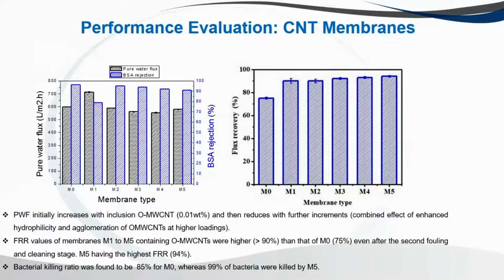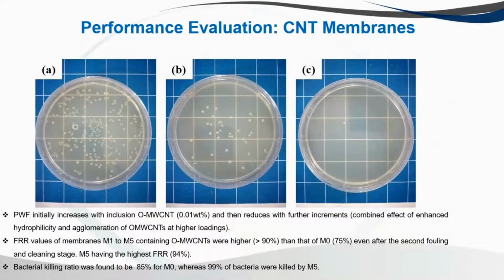The FRR values, which are shown on the right-hand side of the screen, were found to be higher than those for bare membranes. And even after the second fouling and the cleaning stage, M5, which is the membrane with the highest concentration, has the highest FRR value. In terms of bacterial studies, we have found that the bacterial killing ratio was at 85%, whereas it was at 99% when M5, the membrane with the highest CNT loading, was used.